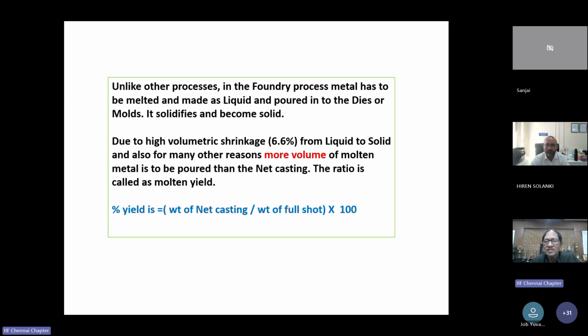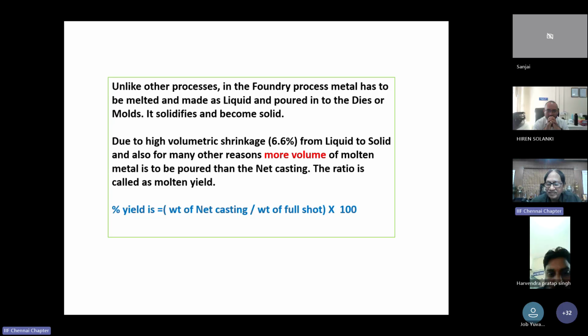Unlike the other processes, in the foundry process alone, metal has to be melted into liquid and poured into the dies or molds. It solidifies and becomes solid. Due to high volumetric shrinkage, about 6.6% from liquid to solid, and also for many other reasons, more volume of molten metal has to be poured than the net casting. This cannot be changed. The ratio is called molten metal yield. Percentage yield is calculated by the formula: weight of the net casting divided by the weight of the full shot, multiplied by 100. So it is expressed in percentage.